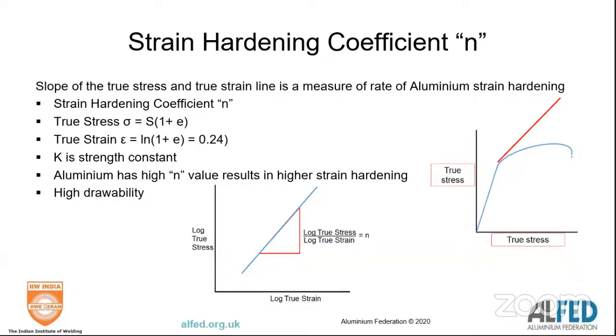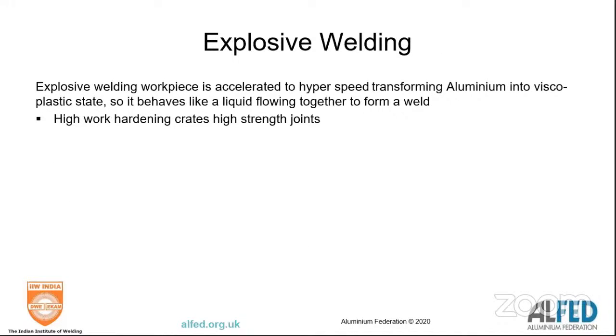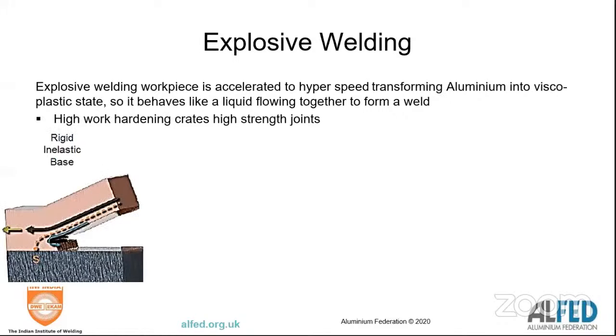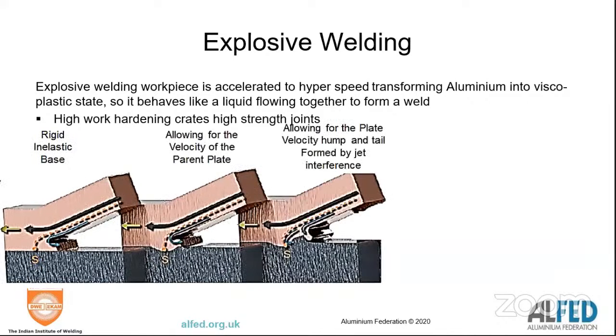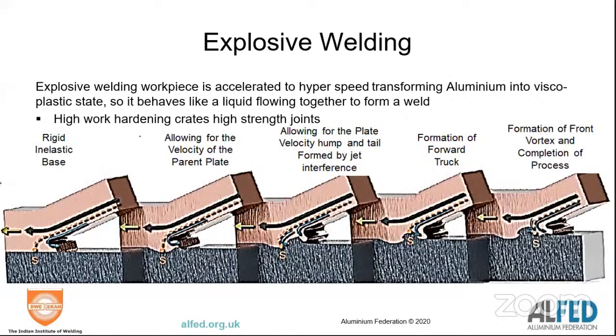We've not mentioned this, but aluminium has a very high work hardening rate. So in terms of work hardening, its n coefficient is very, very high. And a high n value means that it work hardens extremely easily, and it also has high drawability. That becomes important when we talk about explosive welding. We mentioned very early on ultrasonics, micro explosive welding, but in explosive welding, what you do is move metals at supersonic speeds and form mechanical joints. The beauty of aluminium is it's got a high work hardening rate and it's got high drawability. So in an explosive weld situation, it'll work harden, but it'll also move at good speeds.